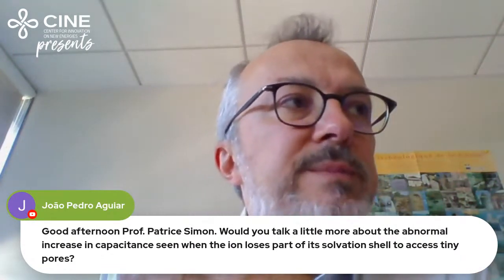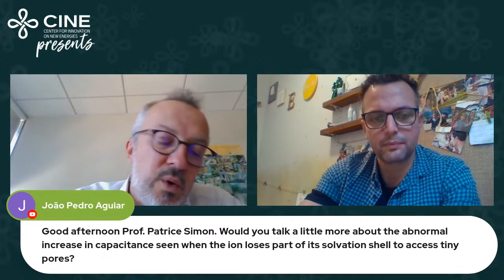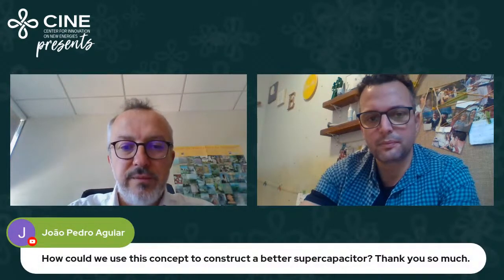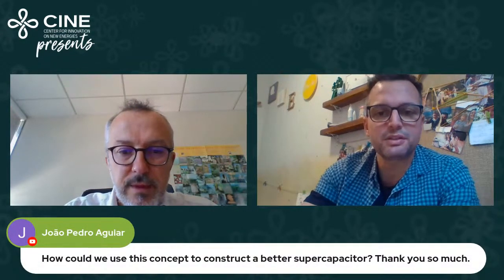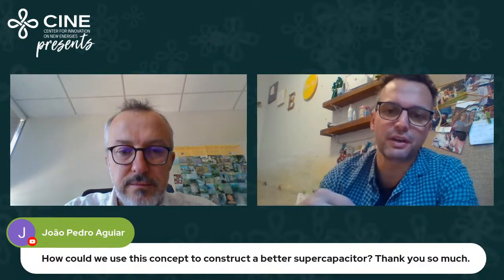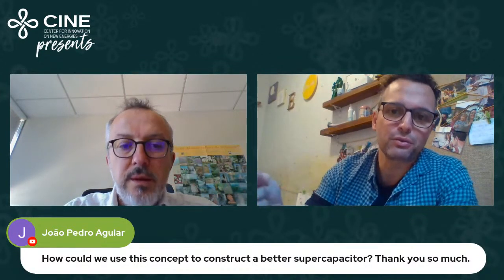And we believe also that this partial desolvation leads to a partial charge transfer from the ion to the carbon. And this is why you have this capacitance increase. Again, abnormal was 15 years ago; now it's something which has been well identified, and this is obviously due to desolvation and partial desolvation. Somehow this charge transfer increases the capacitance a lot, but you also have the issue with the diffusion, right?